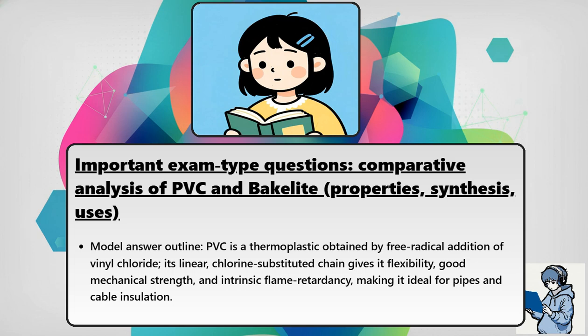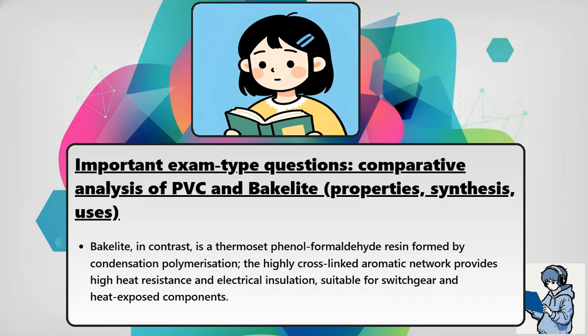PVC is a thermoplastic obtained by free radical addition of vinyl chloride. Its linear chlorine-substituted chain gives it flexibility, good mechanical strength, and intrinsic flame retardancy, making it ideal for pipes and cable insulation. Bakelite, in contrast, is a thermoset phenol formaldehyde resin formed by condensation polymerization. The highly cross-linked aromatic network provides high heat resistance and electrical insulation suitable for switchgear and heat-exposed components.